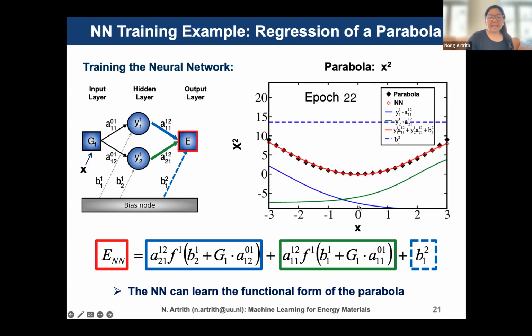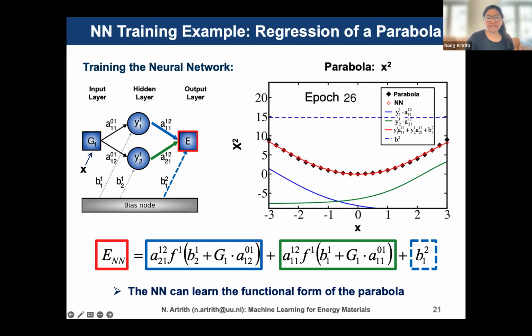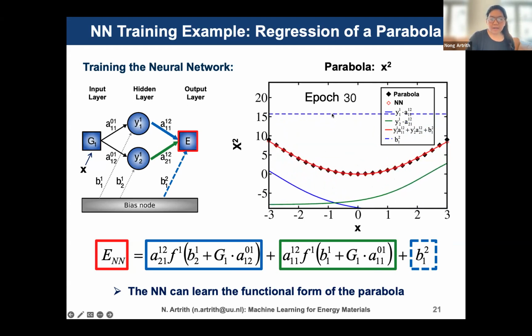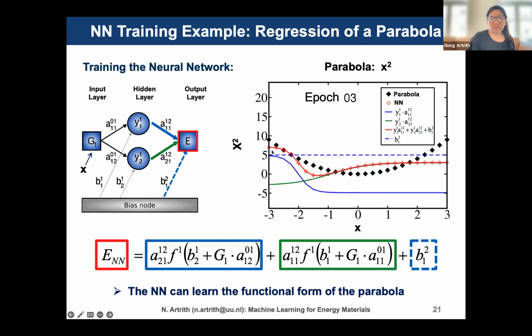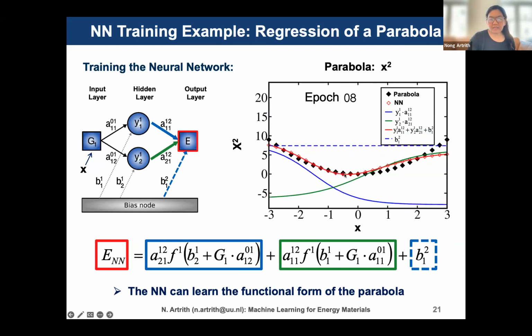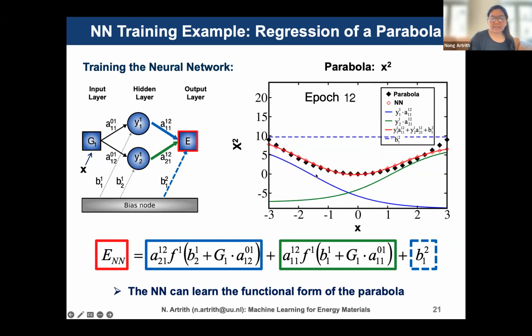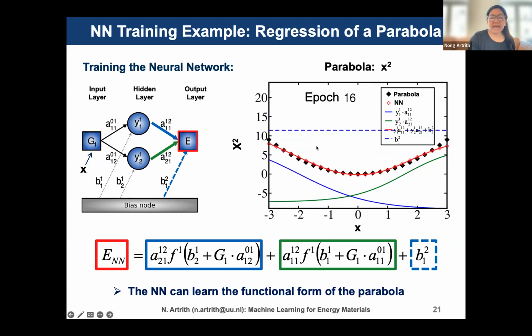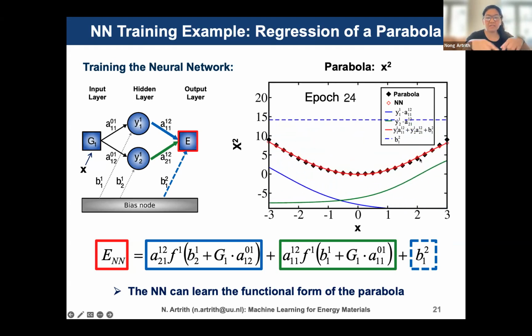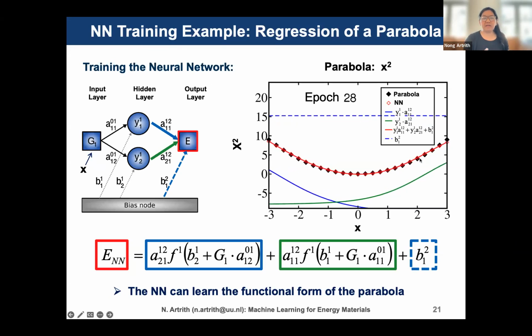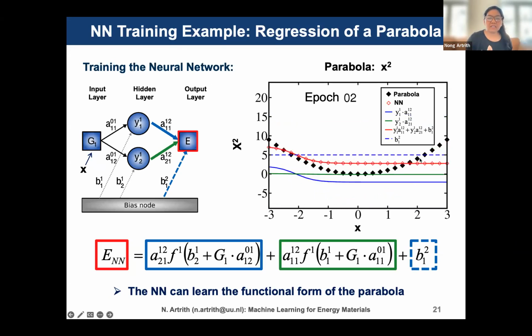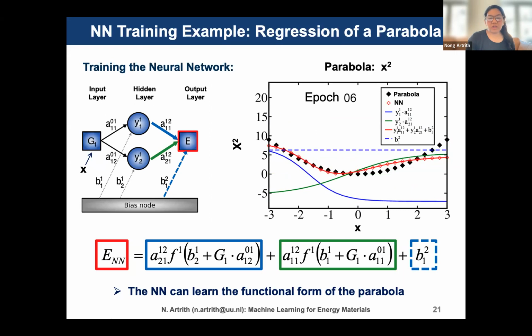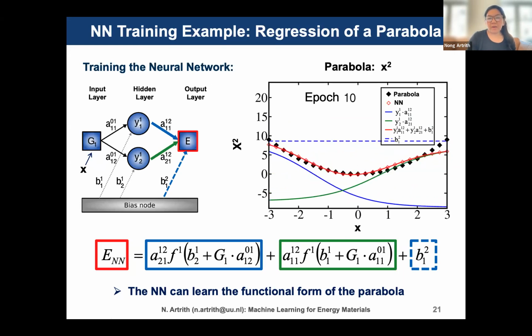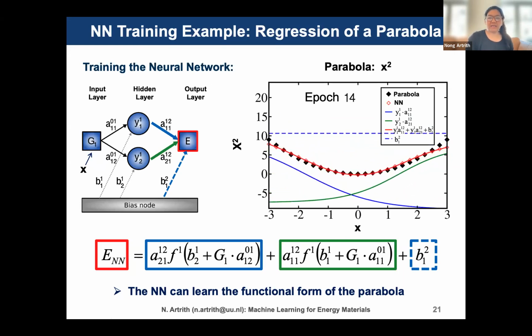And then the combination of the bias, or the constants, shifts the blue and the green nonlinear curves toward the parabola, shown as black diamonds for reference. And then we get the sum of all three terms in the red curve. So after a few iterations, the neural network predicts the parabola accurately, as you can see here.